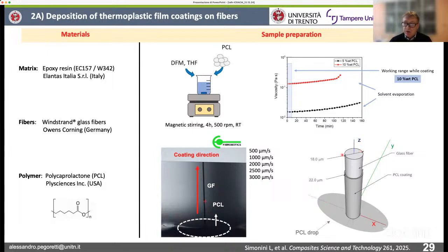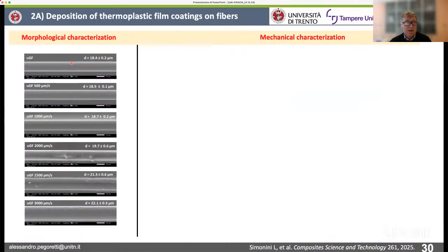According to our determination, the initial diameter of the fibers were 18 microns, and we were able to reach a final diameter of about 22, which was the highest diameter. And therefore, you can evaluate a thickness of the layer of the deposit PCL coating of about 2 microns. Here you can see the initial fibers uncoated. The diameter is roughly 18 micron. And then different velocities of extraction. By changing the velocity, the diameter increases until about 22 microns, which is basically indicating a coating which is quite homogeneous on the surface of the fibers, and it is composed by polycaprolactone.